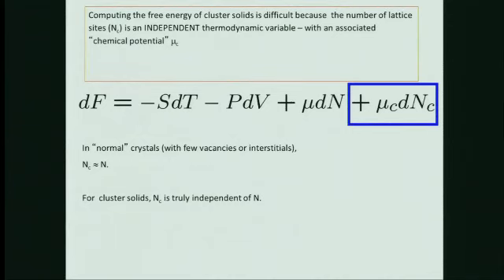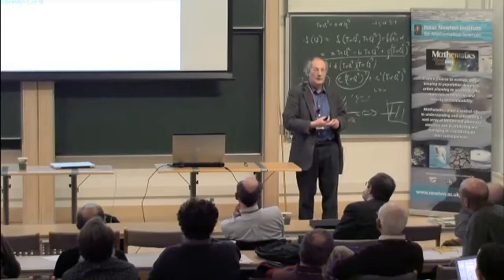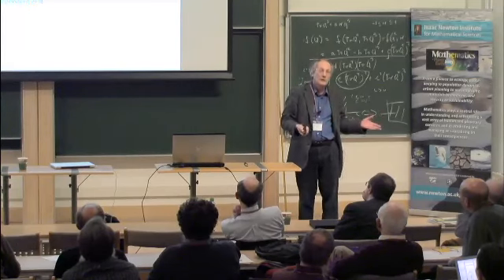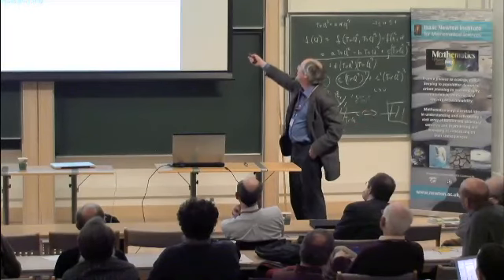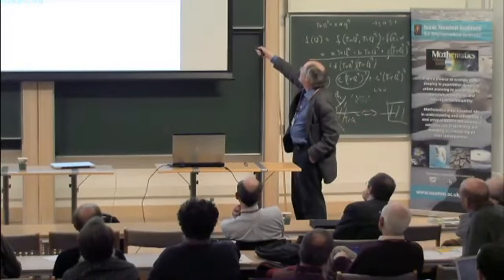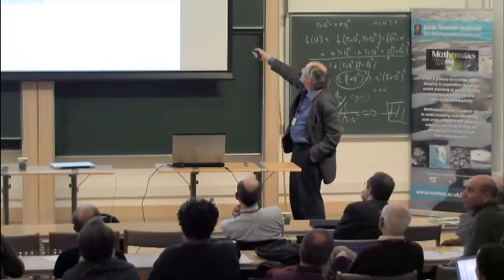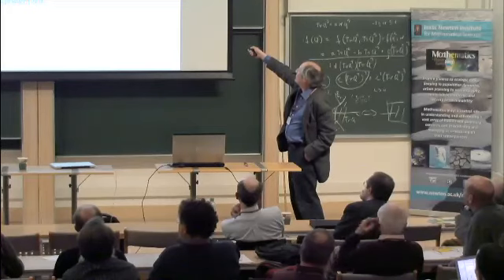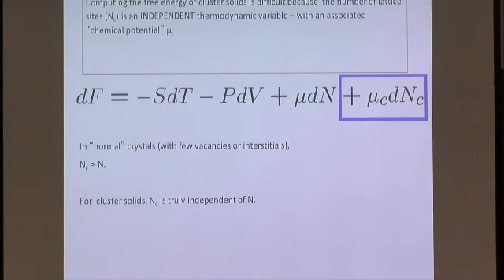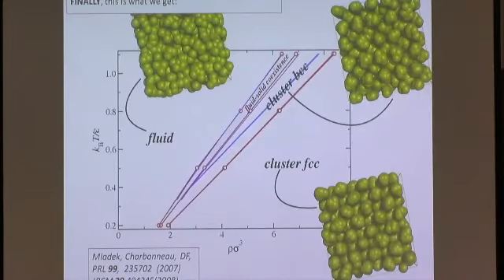It's a bit like if you have particles in contact with a reservoir, that can be deleted and created, the chemical potential has to be 0, because that's the situation where the term in front of the variation in the number of particles is 0. But in principle, in a simulation, if you're not careful, you end up with systems where you've prepared a certain number of lattice sites, it has a finite μc, and all hell breaks loose and you get nonsensical answers.